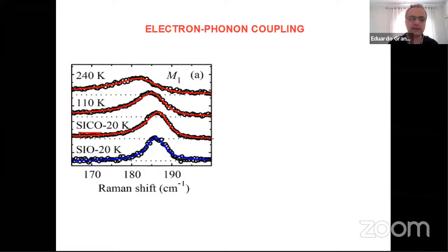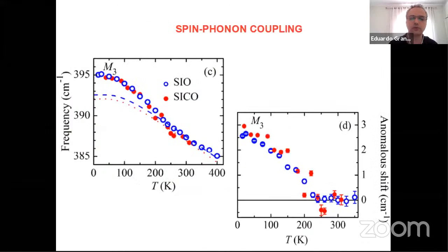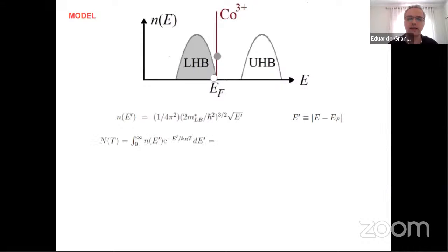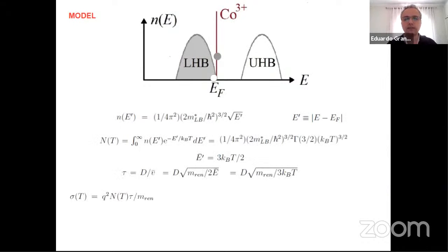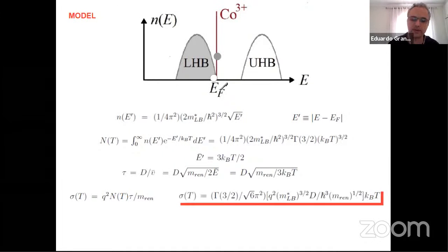So we have these electronic excitations which are very low energy, like milli electron volt. And that suggests that although the material is not a metal, we have very low energy excitations. So now I go directly to the conclusions, and then we have a model for that. We can actually show that this very simple model, where we have this lower Hubbard band and the impurity level exactly at the Fermi energy, describes exactly the behavior that we have in both resistivity and Raman scattering.